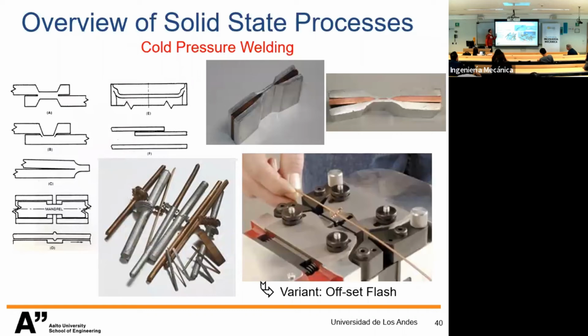In the other extreme, where we have no heat power source, so some heat is generated in plastic deformation, but we can bring together materials that are ductile by plastic deformation. This is the offset flash process for welding wires and structures by specific plastic deformation, bringing chemically active surface that under their mechanical energy activate mostly atomic bonding. You have these Coca-Cola aluminum bottles, beer bottles, everything, welded with clinching and a bit of cold pressure. So you can only apply these in materials that are ductile because you don't have a heat source, and so it relies mostly on the new chemically active surface and on movement deformation.